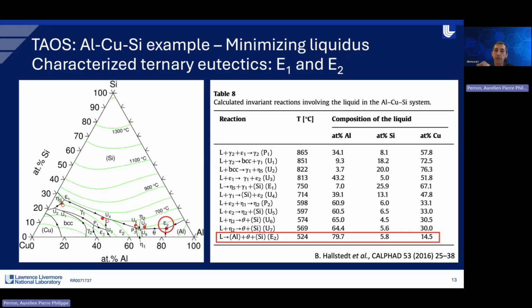You can see that in this system, the minimum melting point is at roughly 500 degrees C, and it corresponds to a eutectic system. So the liquid phase directly transforms into 3 solid phases. It can be interesting for, let's say, some typical microstructure that will form and will give rise to interesting properties. So this is one, but there is another eutectic in this system, much more on the copper side, that we will try to characterize.